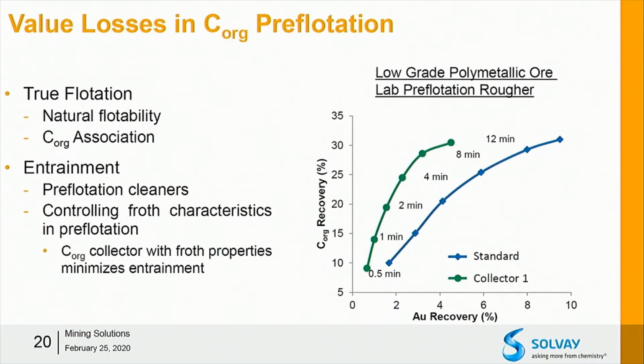I think the best actual method is to use chemical and engineering approaches in concert to really obtain the best metallurgy. But our commercial team developed a carbon collector to match the froth behavior of a carbonaceous polymetallic ore. And what they saw from the testing was actually a reduction in Corg recovery that was entirely due to reduced entrainment because the froth properties were improved significantly.